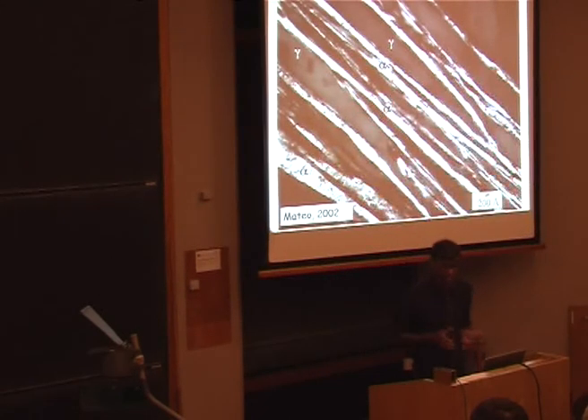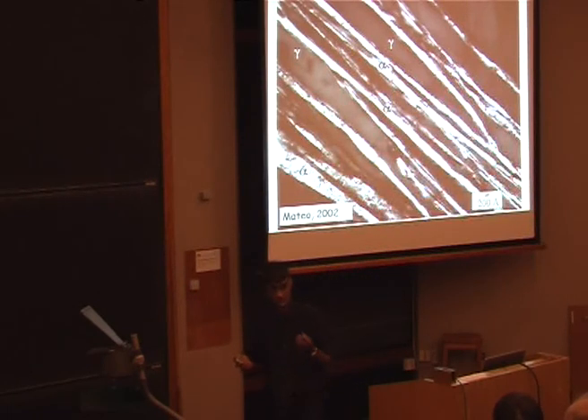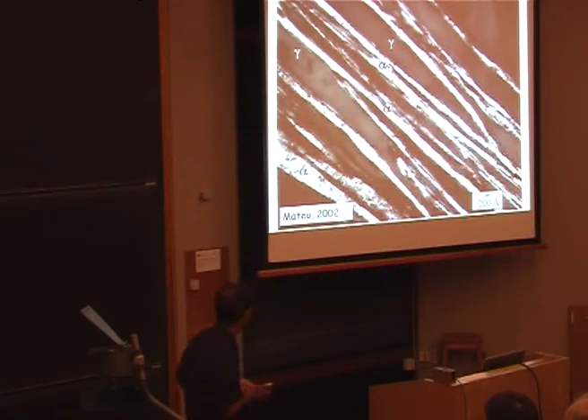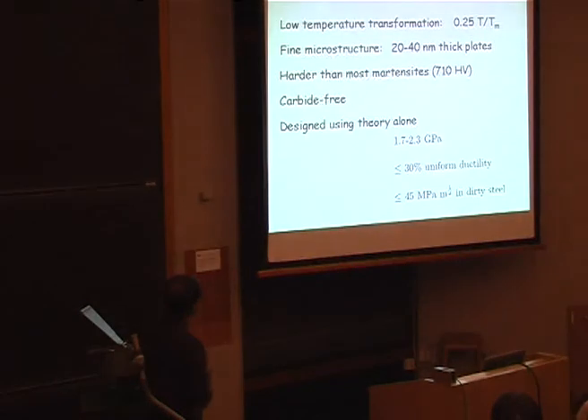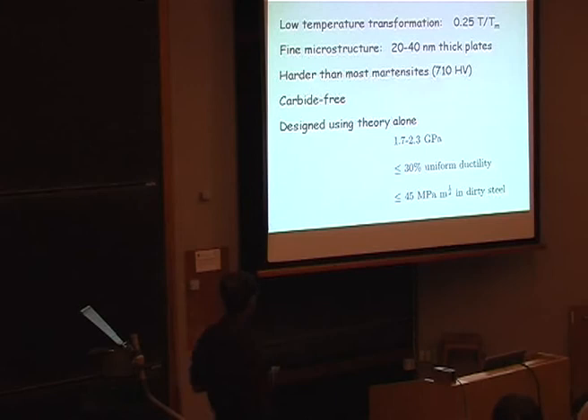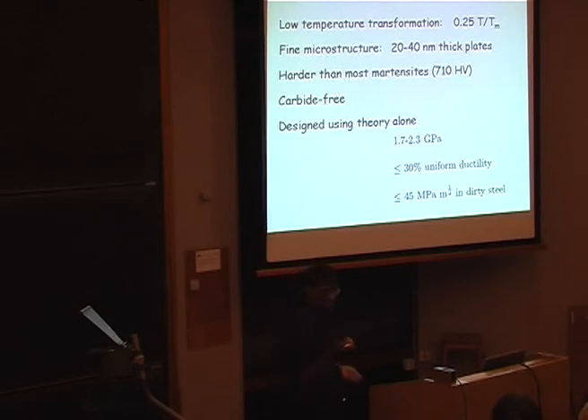So we've got a wonderful mixture of these slender crystals of ferrite. The controlling scale is the same as that of carbon nanotubes, and it's transformed at about a quarter of the homologous temperature, the melting temperature. We have achieved the right scale. This is the hardest ever bainite to produce, and yet it can have enormous uniform ductility and toughness.